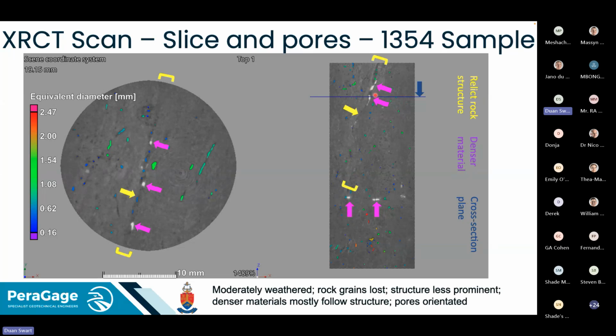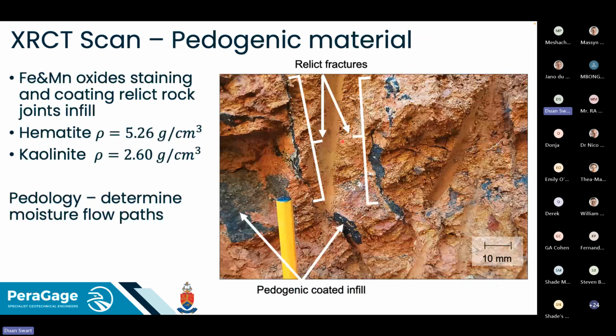And the denser material, which will be your brighter, more white material, solely occurs in these structures. There's another structure running here, left to right. What that tells us, from looking at the logs, the CT scan, and stereo microscopes, is that the relic rock structures have infill, and that infill has been coated and stained by iron and manganese oxides, which is very dense, much more dense than the surrounding kaolinite. That's what stands out on the CT scans.